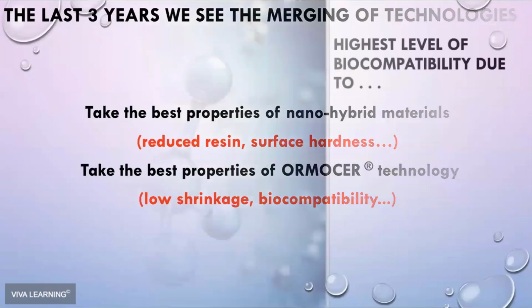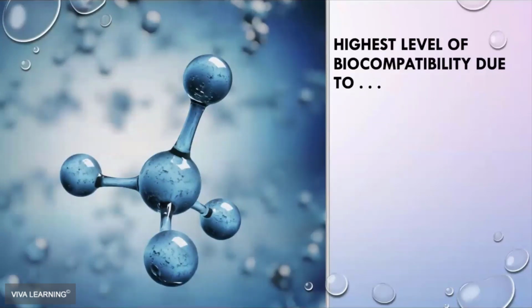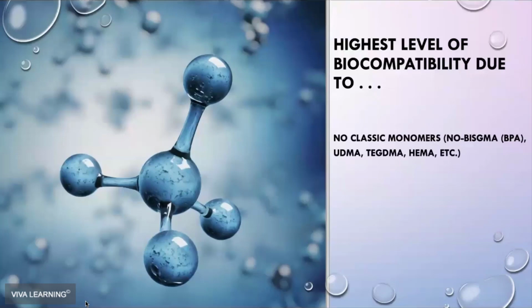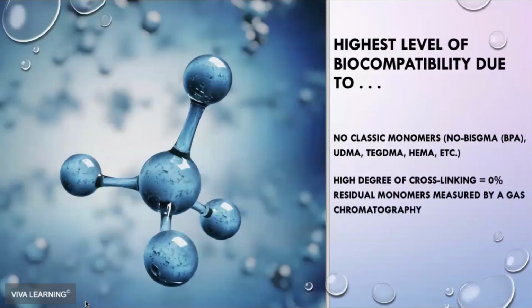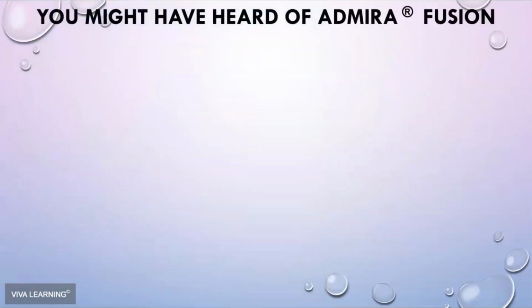Interestingly enough, I'm proud because, with the ORMOCERs that helped develop some of these newer composites, VOCO was one of the leaders in bringing a higher level of biocompatibility to a family of dental restorative material. We're looking at no classic monomers that we've normally seen in the past. And in regards to that silicon dioxide and that matrix of the resin and the glass particle and the inorganic and organic matrix of it, it's leaving us with a very high degree of cross-linkage. 0% residual monomers when you look at the measurements that we're seeing from some of the third parties that have looked at these composite resins. So with that said, we look at a different family of material.